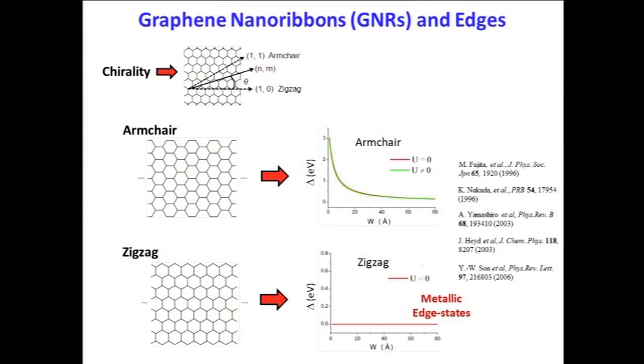And I think that makes intuitive sense because as you make the width narrower, it's like particle in a box. You make the box smaller, you expect the energy level spacing to get bigger. And so for the armchair nanoribbons, you can really think of this energy gap as a size quantization effect. If you turn on electron-electron interactions, it doesn't change things all that much. So you just get that gap. And there's no edge state for the armchair nanoribbons, or at least that's the prediction.